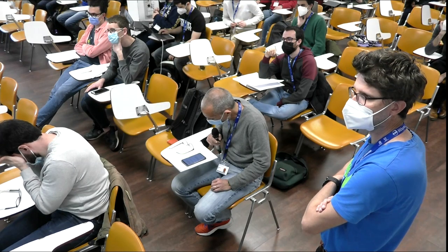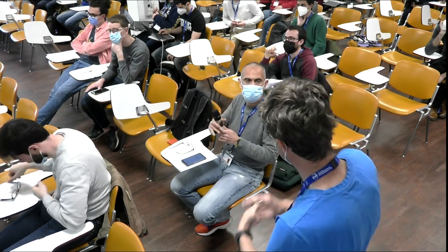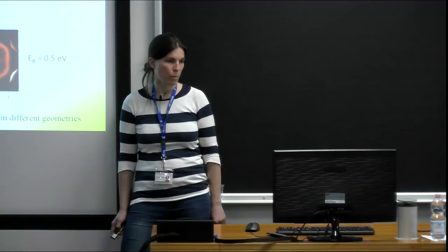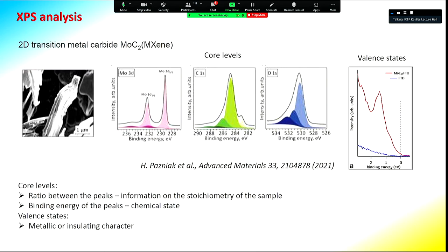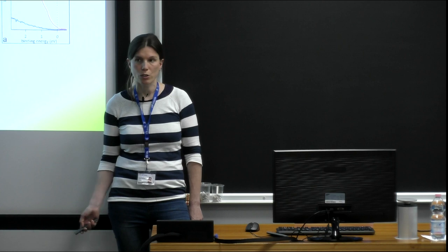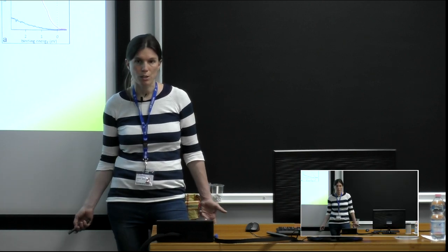How tricky is it to prepare samples for ARPES measurements, and can we control the environment to avoid oxidation? Yes, in the photoemission beamline one can go up to 1000 electron volts to cover the core levels of oxygen and follow any oxidation. The difficulty depends a lot on the sample: some samples like topological insulators can just be brought into vacuum, cleaved, and measured immediately. Other times you can spend several days trying to prepare the surface without success.